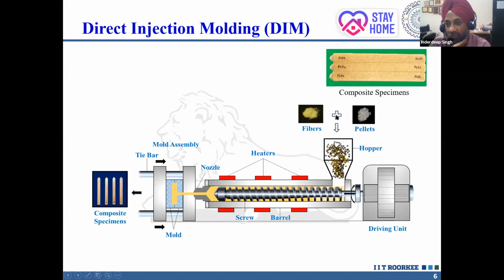We are interested in making composites. So we combine the fibers and the pellets together, and we put these fibers and pellets in this hopper, and we are able to inject the molten or the melt blend, and we are able to get samples like this. These are fiber reinforced, natural fiber reinforced polymer composites.